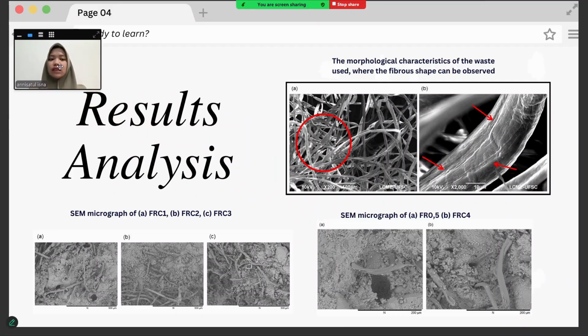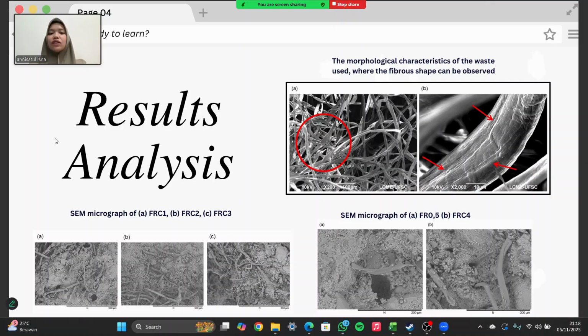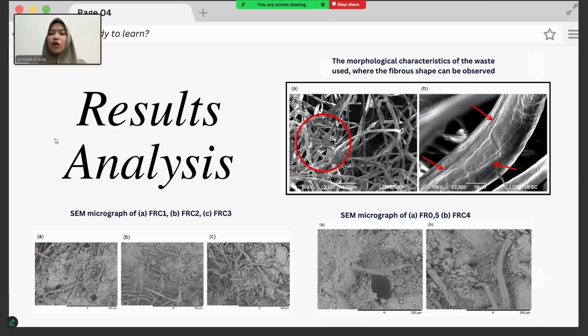This slide shows the SEM results of both the viscose rayon fibers and the fiber reinforced composite. At the top, the micrographs reveal that the waste fibers have a smooth, elongated, and flexible shape, with longitudinal grooves typical of viscose rayon. These grooves indicate a cellulosic structure, which helps in bonding but also affects moisture absorption. In the composite sample, FRC0.5 shows fibers that are well dispersed and strongly embedded in the cement matrix, resulting in excellent bonding and higher strength.